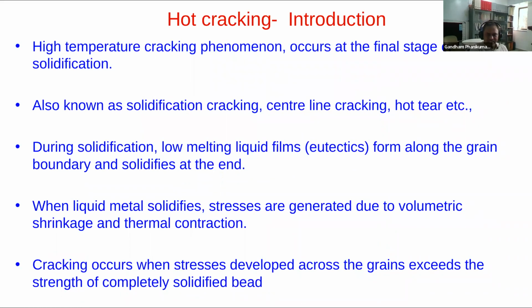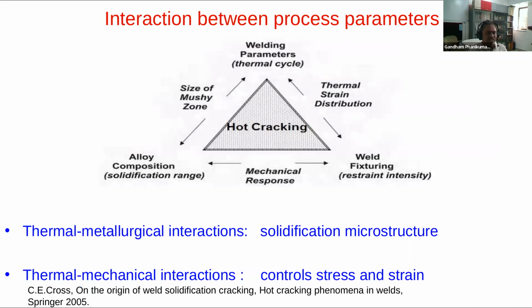Hot cracking, or solidification cracking, or hot tear, occurs towards the final stage of solidification, towards the end of solidification. It is also called hot tear or centerline cracking in the weld, but it's called just hot cracking in the case of additive manufacturing. It occurs because stresses are generated due to volumetric shrinkage and thermal contraction, and that leads to this crack formation. In the case of weld, this is related to the fixturing as well as the welding parameters. In the case of 3D printing, the thermal cycle is quite well established. So you can think of the weld parameters as replaced with the printing parameters, the weld fixturing as replaced with the geometry of the printed component, and the alloy composition with the powder composition. All three can be mapped over to the printing, but the physics of hot cracking remains the same. It's the same problem that is going to occur in the superalloys when you don't take care.